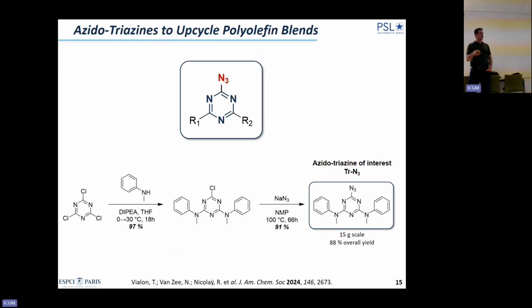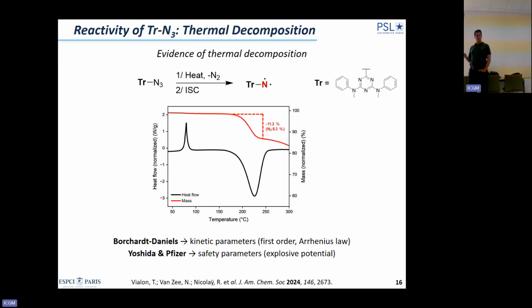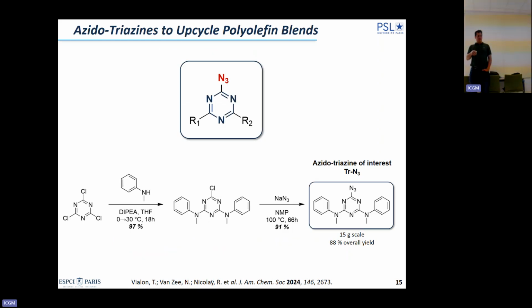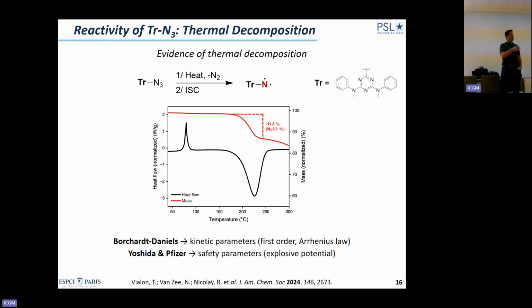So the first thing that we did is to study this molecule. So take a small sample, don't make a 15-gram scale to start, make a very small scale, a few hundred milligrams or even less, characterize the molecule and see if it is safe to scale it up. This is what we did. So how we do this, we do typically TGA and DSC, and with DSC we can access a lot of things. So here in red you have the TGA, so you should look at here, so the mass loss.